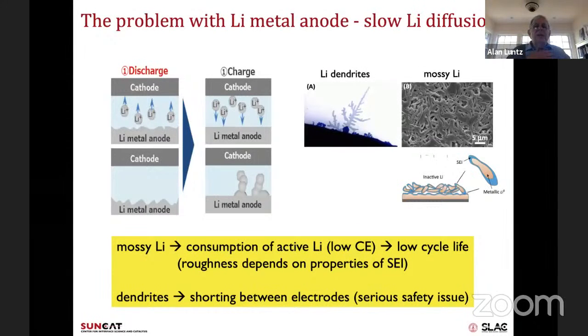So first off, what's the problem with lithium metal? Well, the problem really is that lithium or lithium vacancies diffuse slowly compared to the electrochemical rates you're trying to do. So if you discharge a battery at any reasonable rate, you end up with a rough surface. It doesn't smooth out. And if you charge, even if you started with a smooth surface, you end up with a rough surface again. So if you do this cycle back and forth many times, what you end up with is what's called mossy lithium.